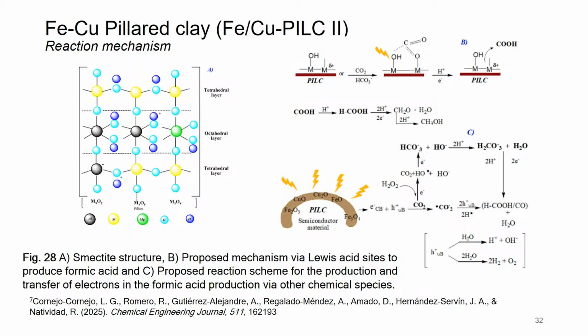You might be thinking, where did the hydrogen peroxide come from? Well, it comes from the use of the light, and also from the combination of the hydroxyl radicals. So we detected the presence of hydrogen peroxide, and of course it's working here together with all the other species to produce the formic acid. Here you can observe the role of the protons and the oxygen vacancies also.